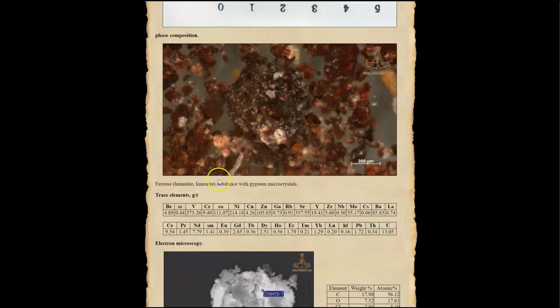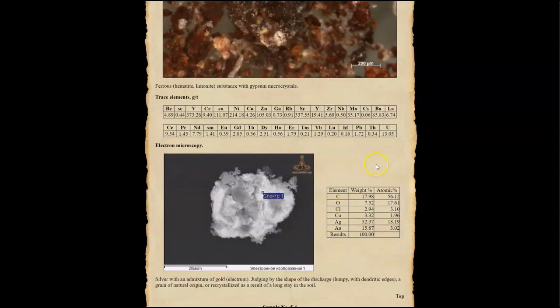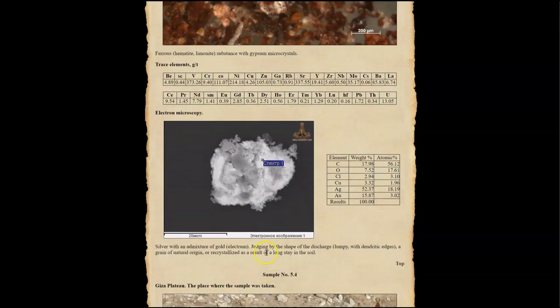No macro analysis was provided on this one, but the trace elements are listed here. And look at what we have here in the scanning electron microscopy scans. A particle of silver with an admixture of gold or electrum, described here as, judging by the shape of the discharge, lumpy with dendritic edges, a grain of natural origin, or recrystallized as a result of the long stay in the soil. So most likely this is a natural piece of electrum, a mixture of gold and silver, but still